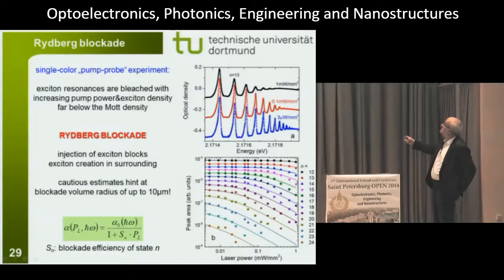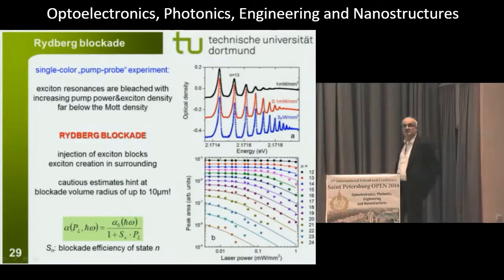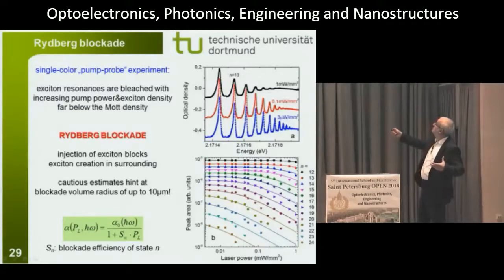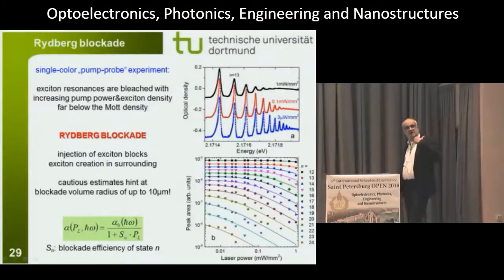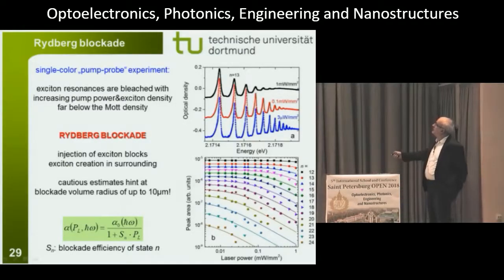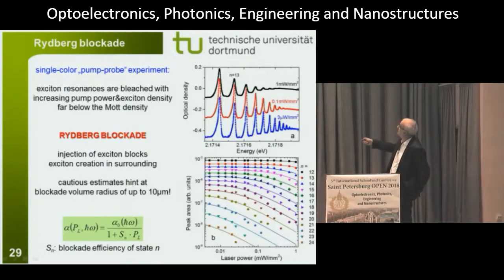What happens here is that we already excite Rydberg excitons, and because of the presence of these Rydberg excitons, you can no longer have absorption by this particular laser here, and your crystal has become transparent. In order to understand this a little bit more, we have integrated over each individual line here, and what we have plotted here is the peak area below each line as a function of the laser power. And you see, as you increase the laser power as shown here, all of these lines start to decrease.